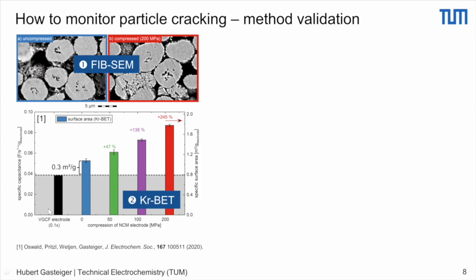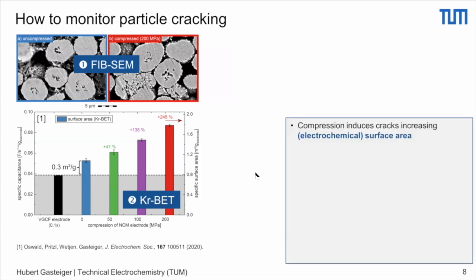contribution from the conductive carbon in the electrode. And so this was done by a model electrode, which only contained the binder and the conductive carbon. And so what we can see is that the remainder here is the BET surface area of the CAM in the electrode. And this agrees actually very well with the powder here. And as we compress this, we see that the BET surface area increases as we crack these primary secondary agglomerates more and more. So what we find, of course, nothing unexpected: compression induces cracks, and this increases the electrochemical surface area.